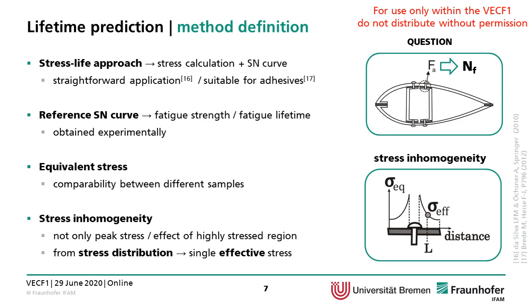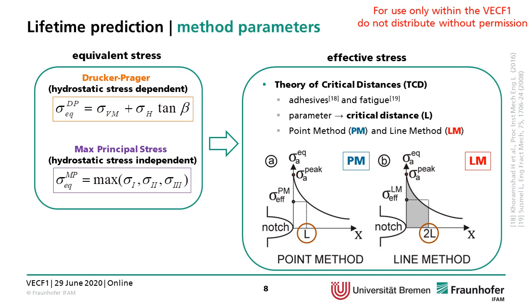different types of samples will have different types of stresses, and the use of the nominal stress approach is not enough to compare two different types of samples. And a method must be chosen to address the stress inhomogeneity, because as you can see here on the right hand side, when you have a stress concentration, you have a distribution of stress. So from this stress distribution, one single effective stress must be taken out to represent well this stress distribution. And once again, the question that we want to answer is, given a particular force amplitude, what is the fatigue lifetime. So now the method parameters.